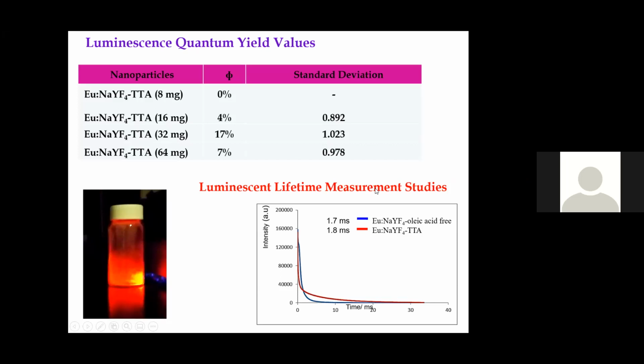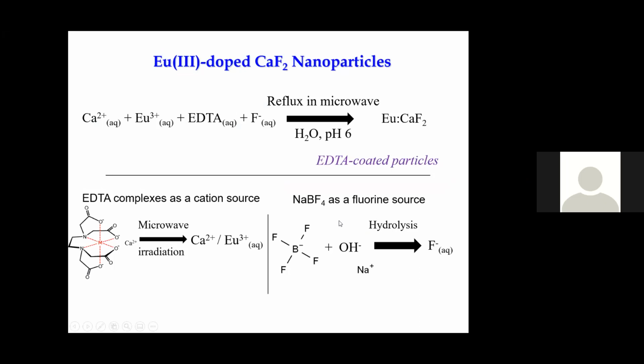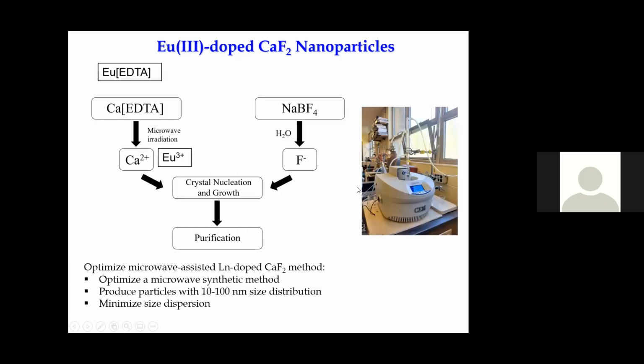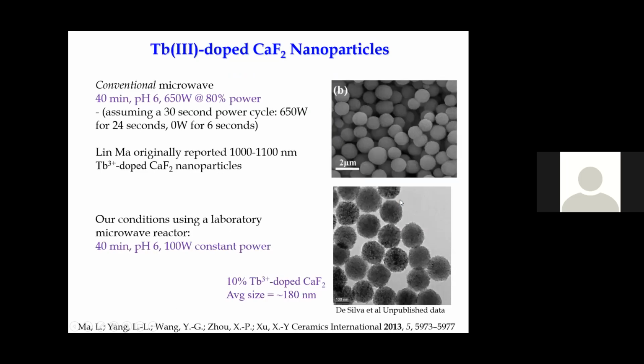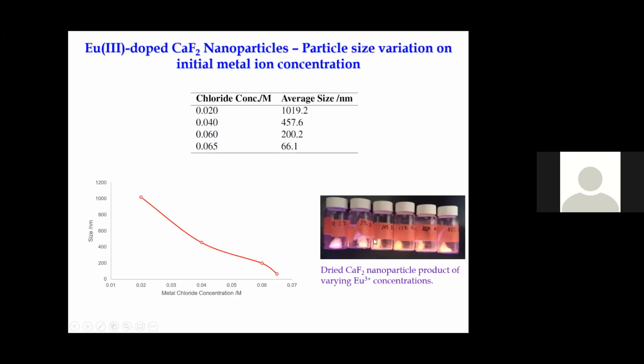We also measure the luminescent lifetimes. They are pretty high for these materials, which is an advantage for these materials. Now we shifted our research to make other matrices like calcium fluoride, which can be biocompatible. Biophysical fields are very demanding these days, coming into the picture. So we wanted to make some europium calcium fluoride nanoparticles. We use a microwave method, like a scientific microwave, to give uniform radiation. Then we got these nanoparticles. You see all of them are the same size, a very impressive method of making nanoparticles.